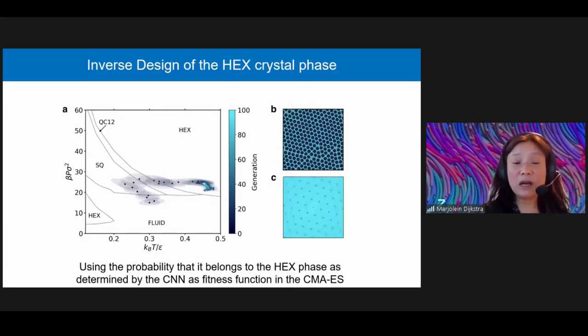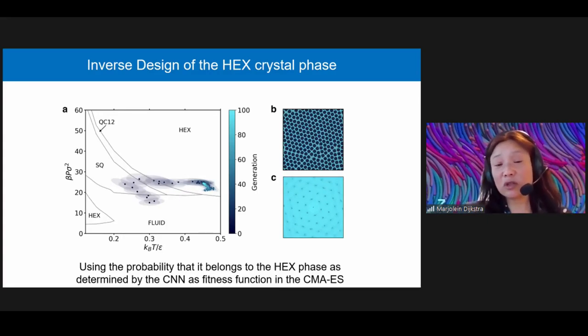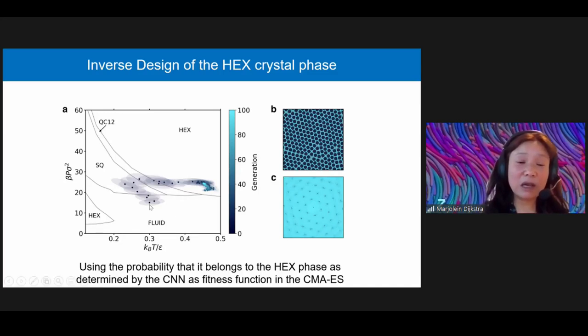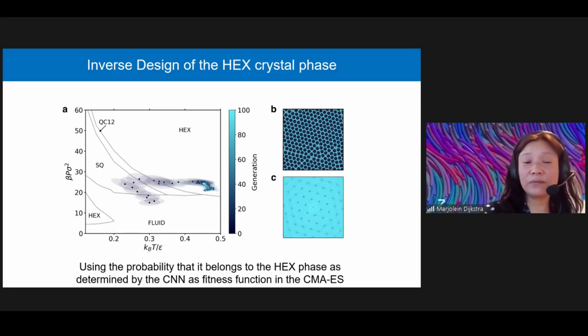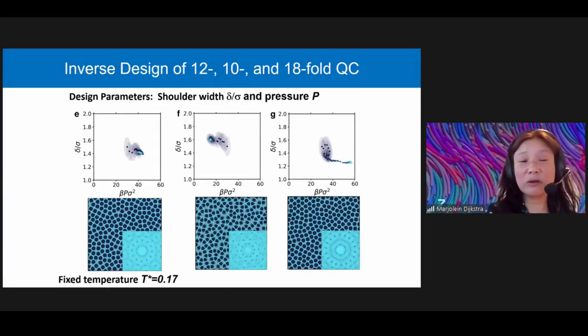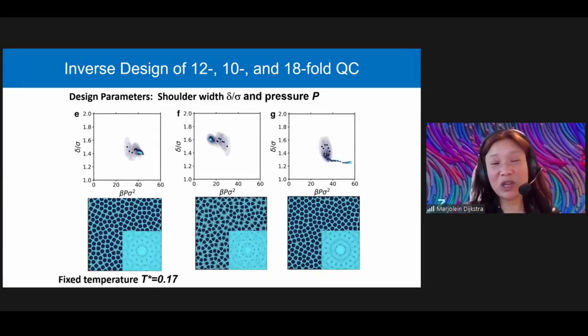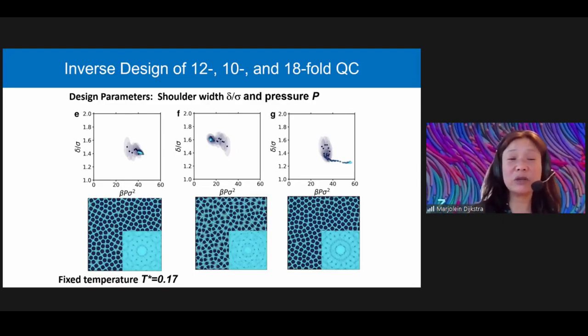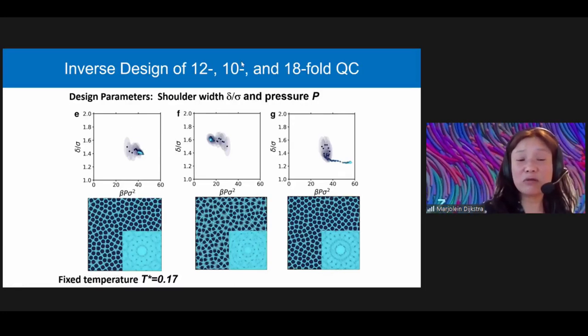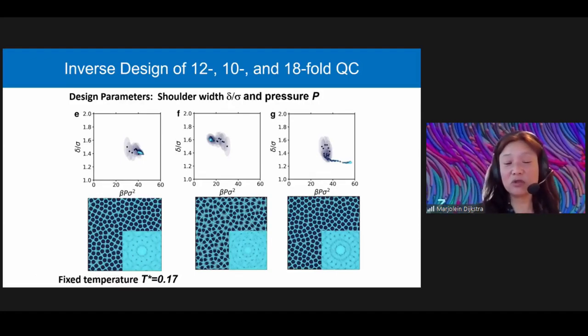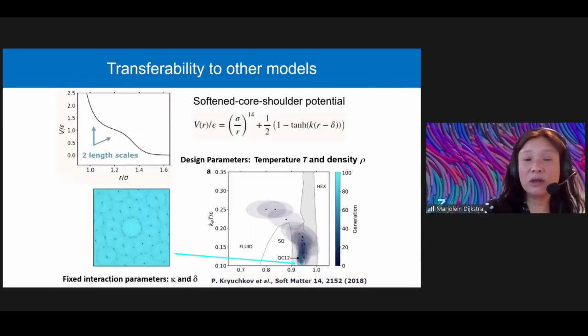We can also take the other output node, for instance, that corresponds to the hexagonal crystal phase, and then our inverse design method is able to also inverse design the hexagonal crystal phase. We can also see how it transfers to other model systems. We can also look at changing the shoulder width as the design parameter. And also in this case, we were able to inverse design the 12, the 10, and the 18-fold quasicrystals.